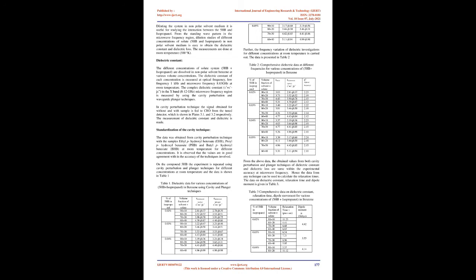The structure of 5-HB is shown in Fig. 1. B. Measurements. 5-HB is dissolved in isopropanol in various concentrations. The various weights of 5-HB for each concentration are given for 26.5 ml of isopropanol. The mole fractions of 5-HB in isopropanol are 0.02, 0.03, 0.04, and 0.05, with weights of 5-HB of 1.62949, 2.46943, 3.32688, and 4.20237 grams respectively.